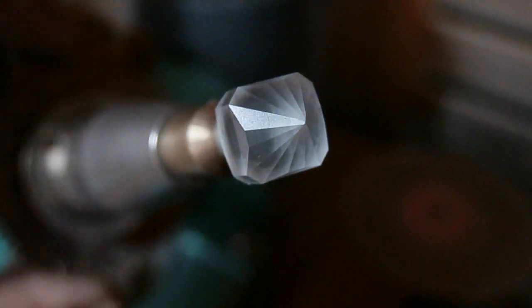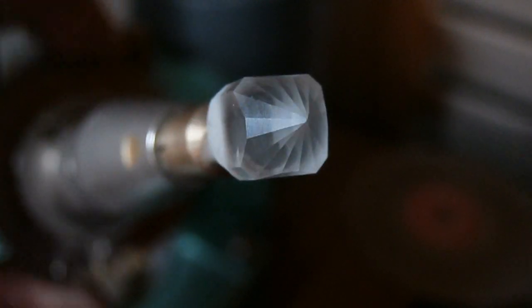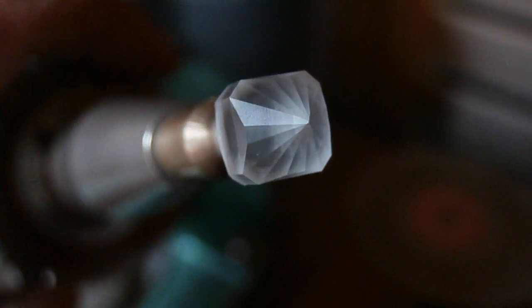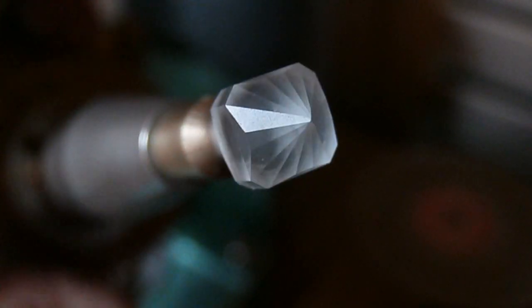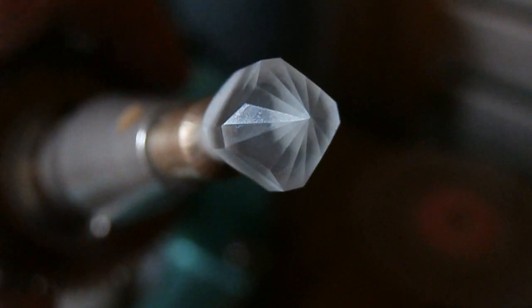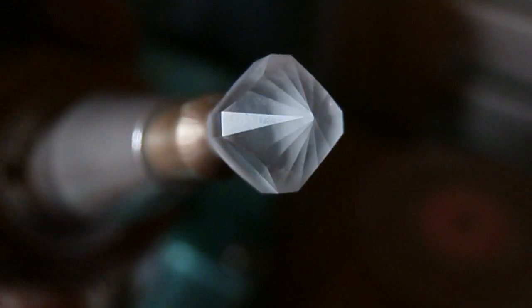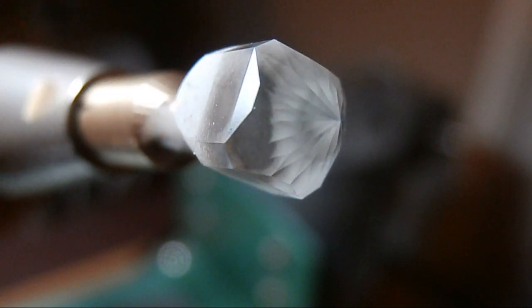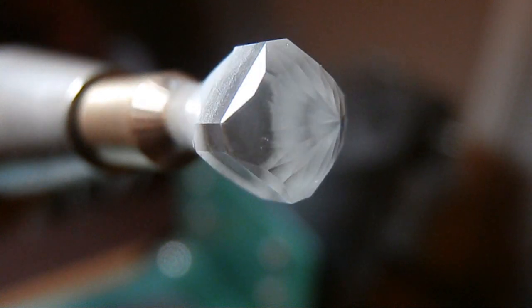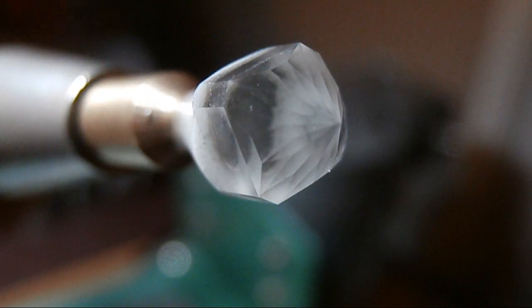In this scene I've used a 3000 grit diamond disc at 73.31 degrees to set the girdle level and you can see that I've cut four facets to even out the girdle. In the following scenes I've cut the last two tiers of pavilion facets at 43.15 degrees and 41 degrees respectively. I've only used a 3000 grit diamond disc.